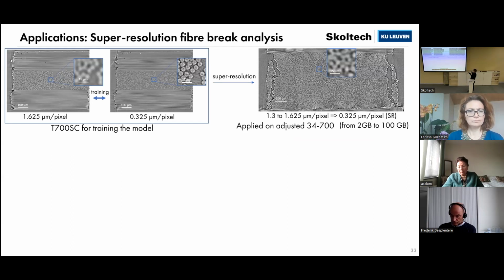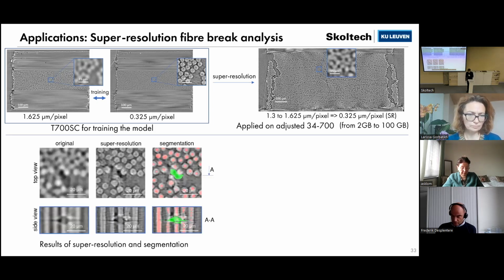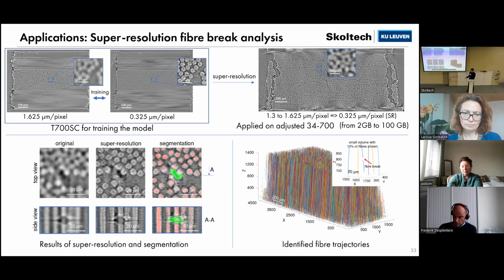After the super resolution, the amount of data was increased from 2 gigabytes to 100 gigabytes, so it's almost 50 times larger. Here you can see the results of super resolution and fiber break identification. In the first row you can see the original low resolution images, then how it was increased, and in the last row how objects were identified, also using deep learning algorithms. We can see how fibers were identified quite well. All the breaks were found, and all the voids were found as well. All the fiber trajectories were constructed, and when we have a void between these fiber breaks, we identify this fiber break.